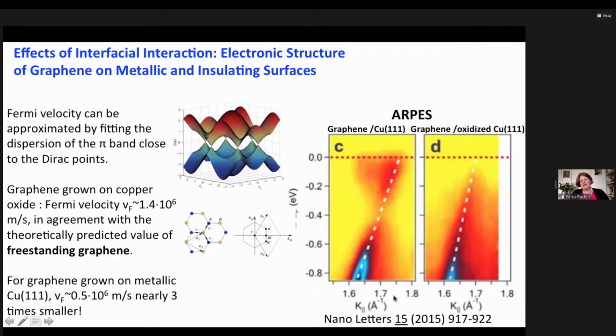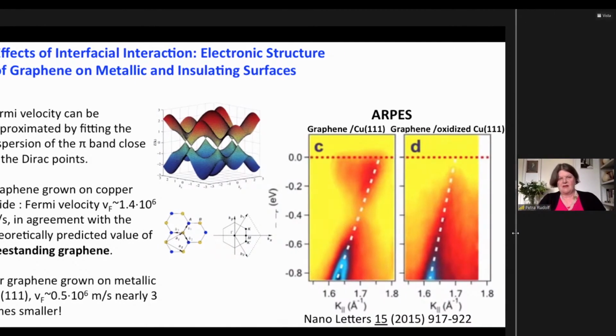Instead, if you could see what is below our photos, namely the dispersion on the copper oxide, you would see that now this point moves up, and it's actually behaving like freestanding graphene in this case. What is also very nice is that the Fermi velocity on the graphene grown on copper oxide is in perfect agreement with the theoretically predicted value of freestanding graphene, while on the metallic surface it is 3 times smaller. So actually we can grow graphene on the oxide in a way that we have graphene that behaves like freestanding graphene, so that we have no influence from the substrate, and that's very nice.